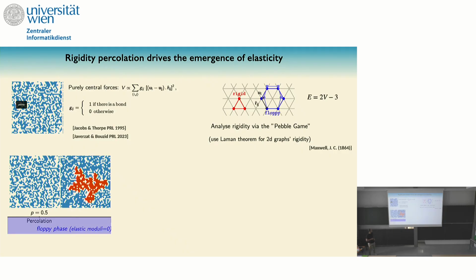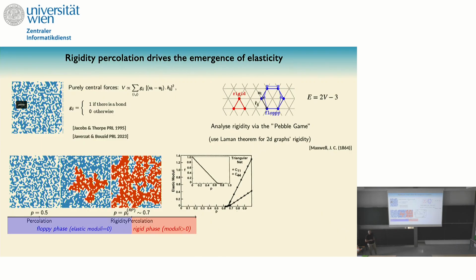Then if you keep increasing your density, at some point you would see some rigid clusters merging. Here I'm highlighting one of those rigid clusters in this system. But still, this rigid cluster is in a system that percolates, but it's not rigid. It has connectivity percolation in the sense that if you send a current from here, you would get something on the other side, and if you try to find a path from here to here, you would find a path. Still, your system is not rigid. If you keep going, at some critical volume fraction, this rigid network will also percolate, and you have a second transition. This is what I call a rigidity percolation transition.